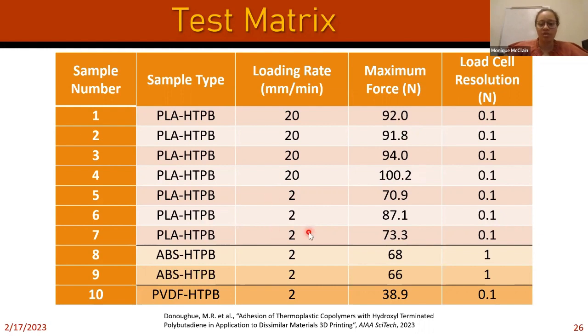But the key thing here is looking at, for the same loading rate and for the different materials, we're starting to see some quantitative differences here, or maybe more qualitative, I guess. We're looking at the peak force when those two are peeled apart, the peak force of the wedge that's being measured. So we got somewhere in the 70 to 80 range here. This is more in the high 60s range, and this is much lower for the PVDF, which is what we were hoping to see because it's not going to bond as well.